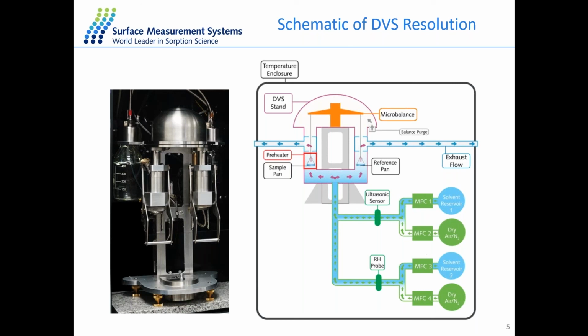Liquid nitrogen temperature has some extreme conditions, and also degassing with the vacuum can empty some of the pores. So in that case, you may measure a bit smaller surface area compared to the nitrogen sorption technique. But in most other cases, most of the samples, we do have very comparable results with the nitrogen sorption. And especially for some low surface area materials, the DVS method is more sensitive, and with nitrogen sorption, in that case, you may need to use some other probe molecule like krypton to get more accurate results.